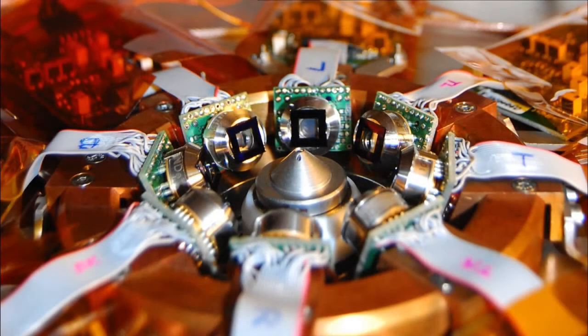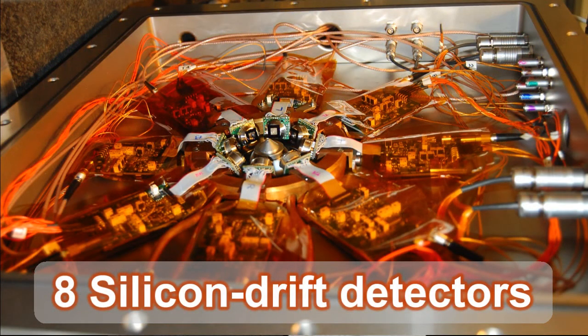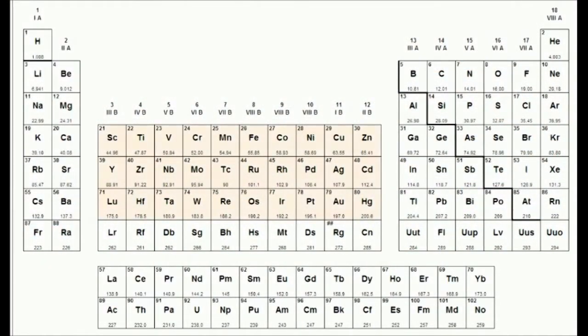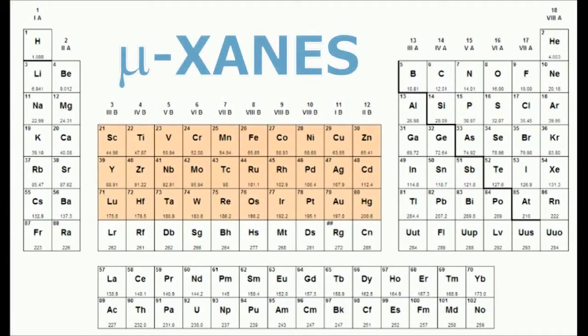In 2008, we started developing the first worldwide low-energy X-ray fluorescence system, coupled with the scanning transmission mode. The setup, 8 silicon drift detectors facing the sample, was finalized in 2010. In addition to X-ray fluorescence, we perform X-ray absorption spectroscopy, in particular on transition metals.